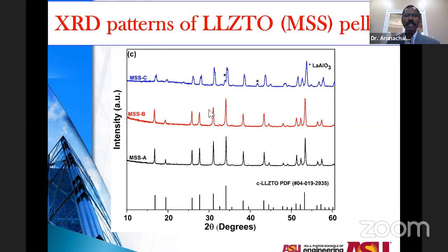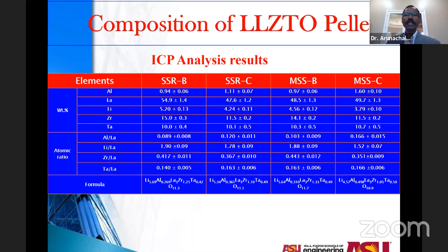In the case of the alumina crucible, it has been reported that aluminum can actually diffuse from the alumina crucible because of the extremely high temperature, almost 1200 degrees Celsius. ICP analysis was carried out to ensure that the expected composition was obtained.